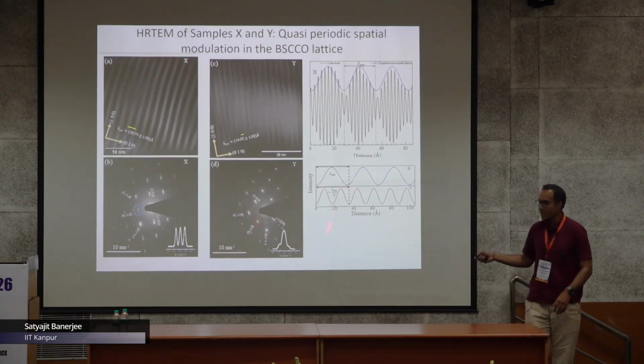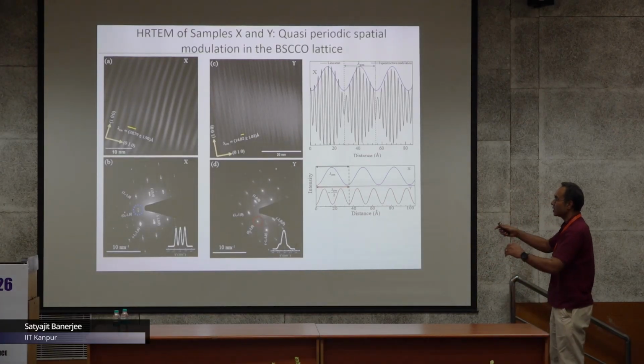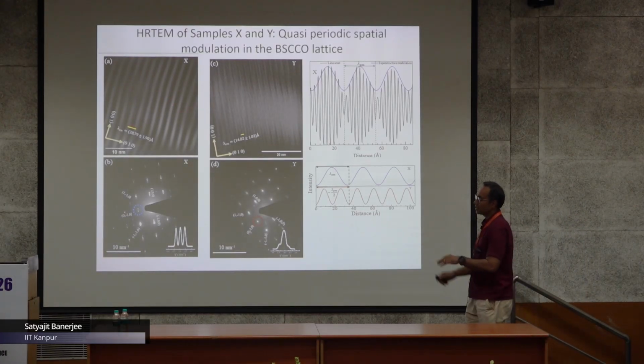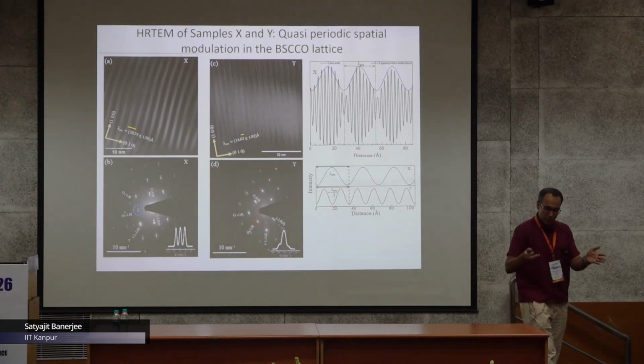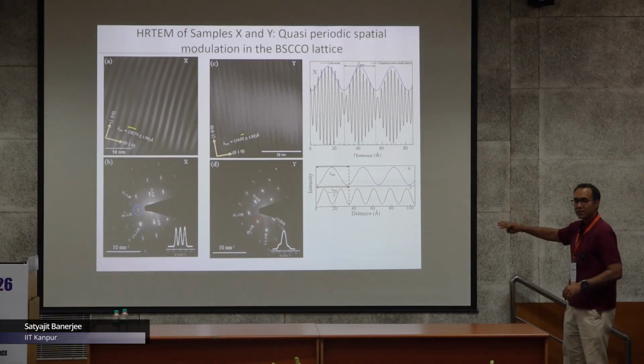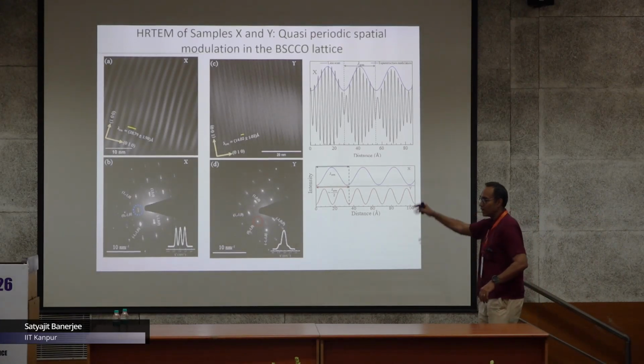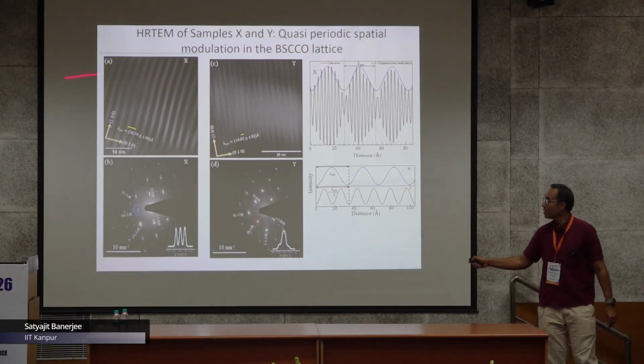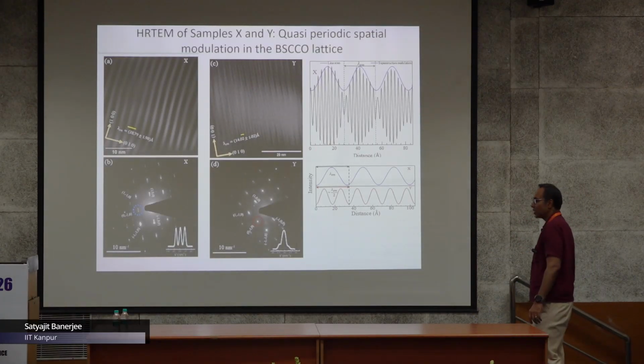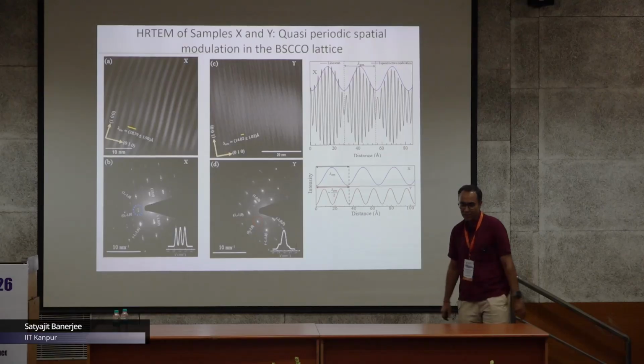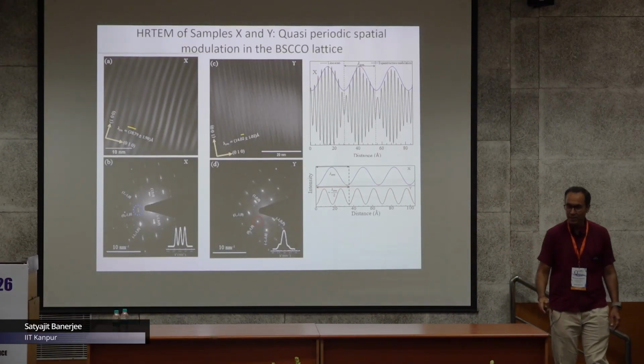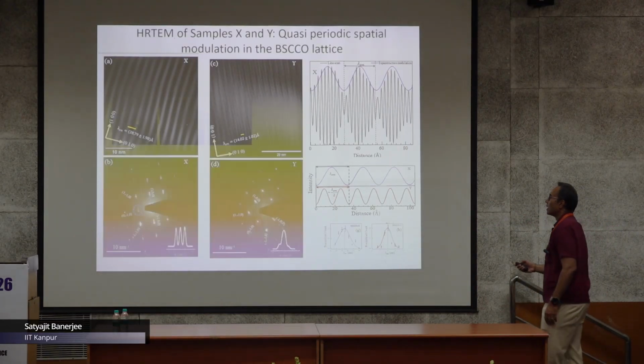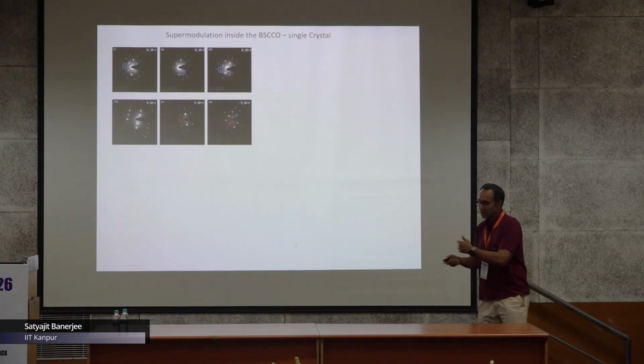So we could actually measure these modulations. You have crystal X, the 2223 phase, which shows a modulation inside the crystal structure, and if you do annealing on the same crystal, you can destroy this intrinsic modulation. And of course there is more data.